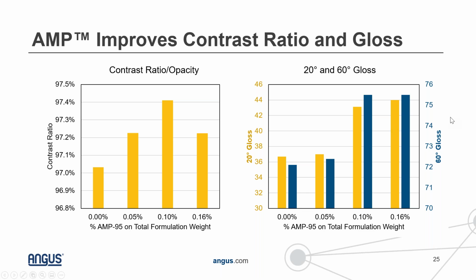This is the graph on the right, and we're showing both the 20-degree and 60-degree gloss. The 60-degree gloss is in blue, corresponds to the y-axis on the right, and the 20-degree gloss is in the dark yellow, which corresponds to the y-axis on the left. But in both cases, we saw an improvement in the gloss with higher use levels of AMP in the grind. And in the case of the 20-degree gloss, we're seeing an improvement of around 8 units, which is noticeable.